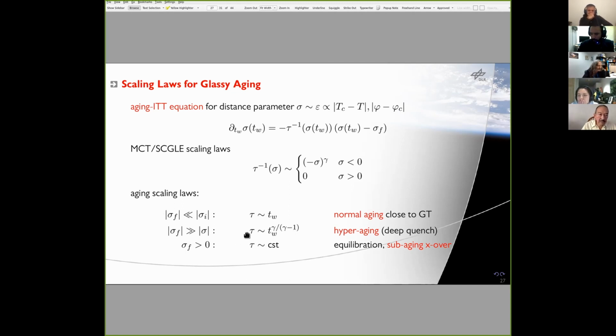And if you then balance the powers, you discover a rather interesting prediction that the structural relaxation time is predicted to depend on the waiting time to the power of gamma divided by gamma minus 1, where gamma is the exponent of MCT. So this is the equilibrium exponent, and out of this you get a scaling law for the non-equilibrium evolution of the relaxation time.